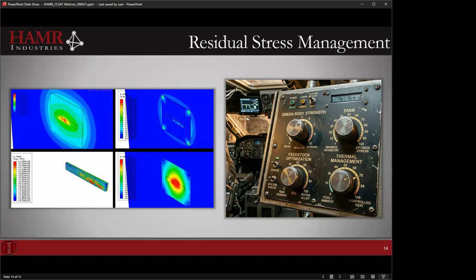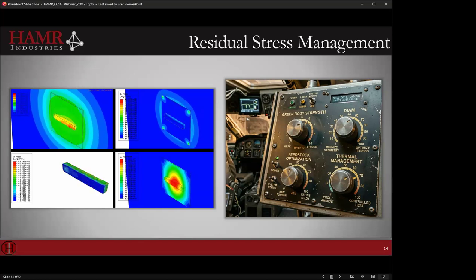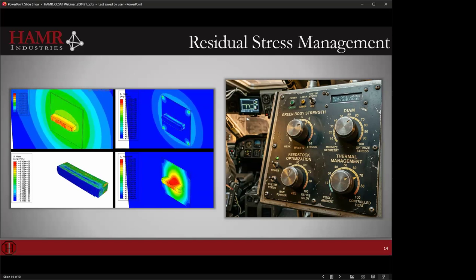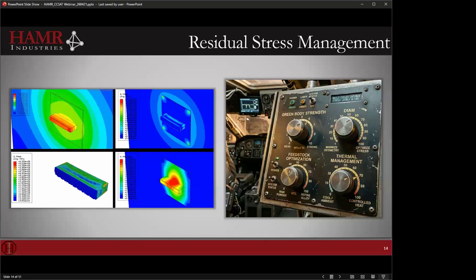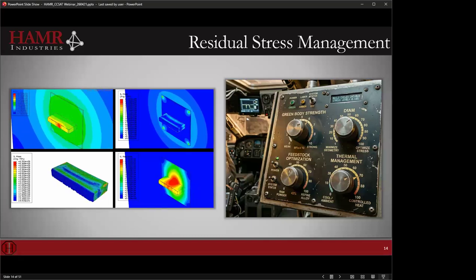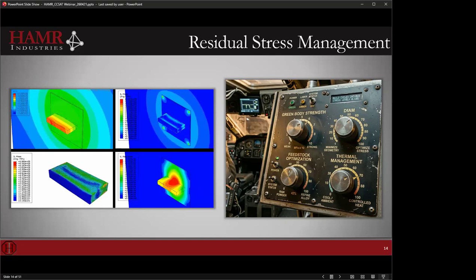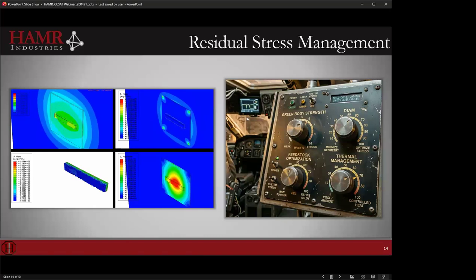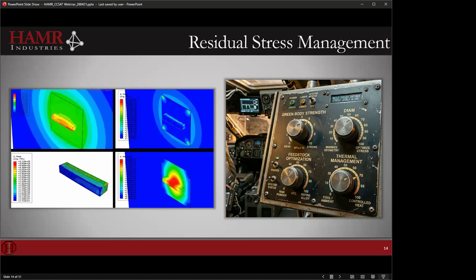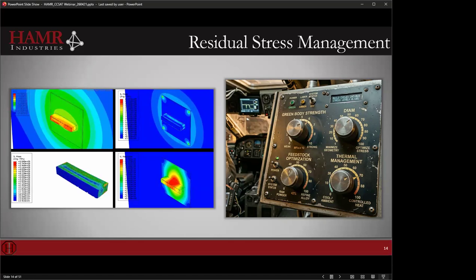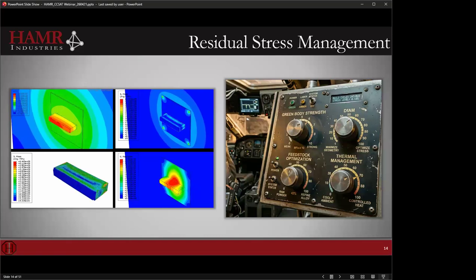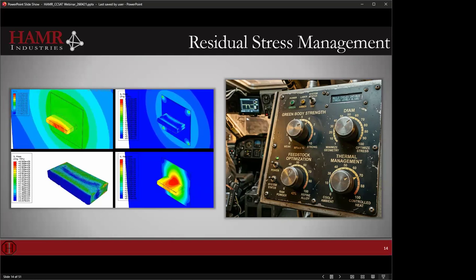So from the green body strength perspective, I mentioned earlier in CSAM, it's ideal to spray with air because when you spray with air, you have the most economical process. The downside of spraying with air is unlike spraying with helium at really high pressures and temperatures and getting something that's ductile off the bat, we have something that's brittle. There's effectively no elongation. So if the stress exceeds whatever the UTS is of your green body, you will have cracking. So what can we do to modify the green body strength? Turning that knob. That's changing process variables, also relates to feedstock.